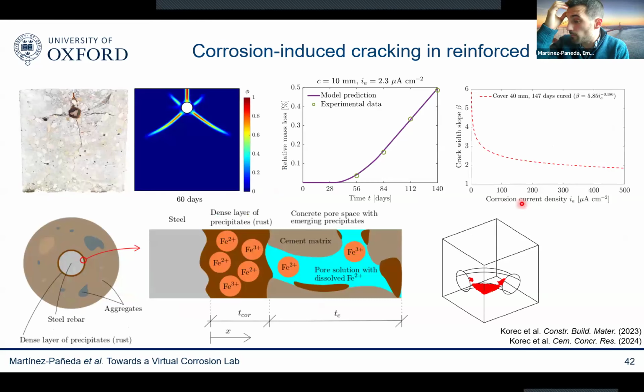We have also used this to tackle that problem that I showed you at the very early beginning, going all the way from those accelerated corrosion current tests that we do in the lab to predicting what happens over decades. And because we can capture the kinetics of the problem, the physics of the problem, we can show that it's very different from that linear interpolation that I showed you before. But we can capture what are the rate limiting phenomena. We can capture the transitions from one mechanism to the other. And we can go from those fast, impressed corrosion current tests in the lab to predictions over realistic time scales. And this is work mostly done by my student, Eugen Korek.